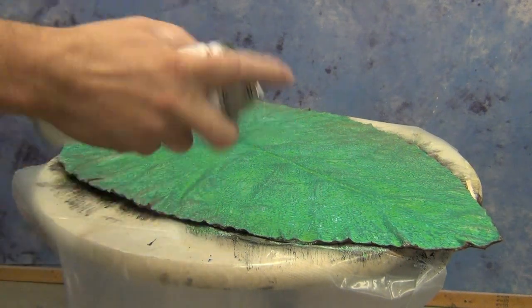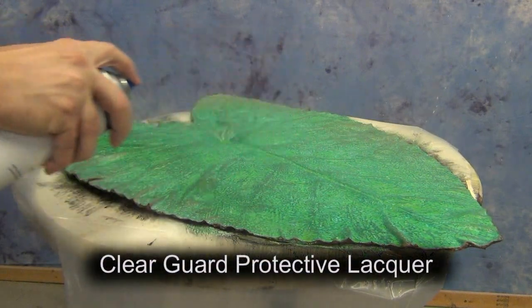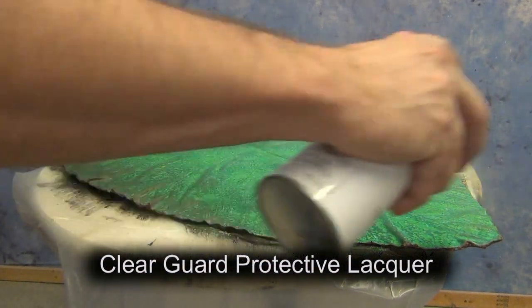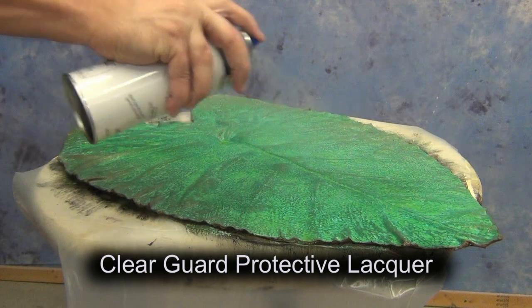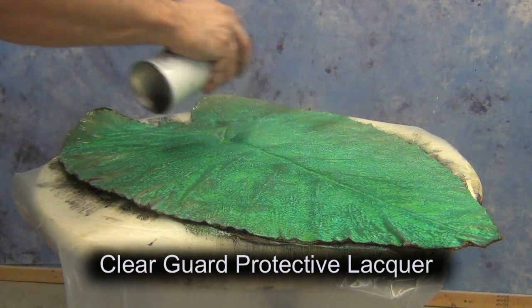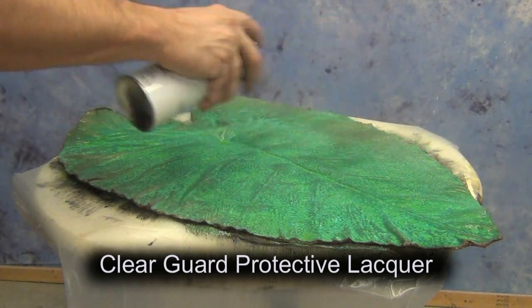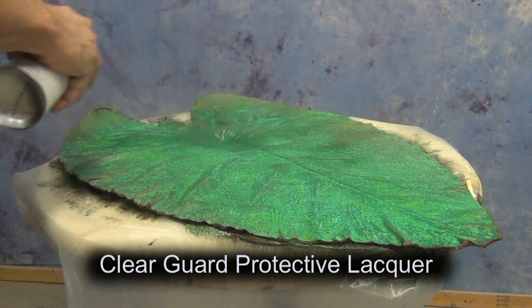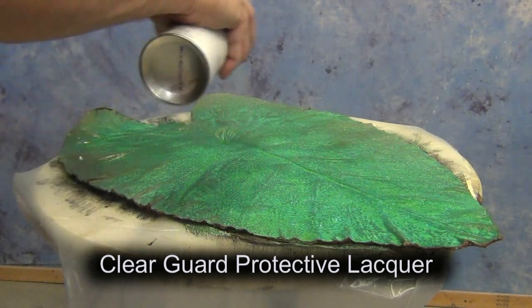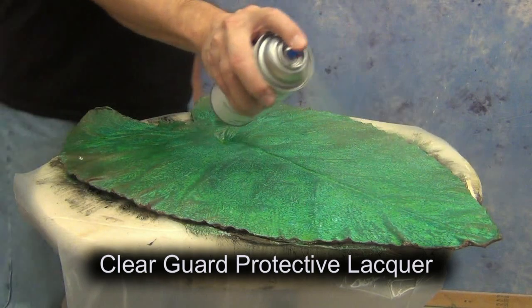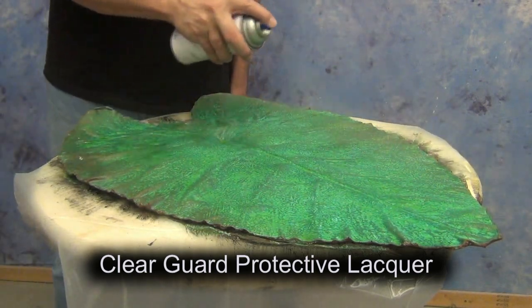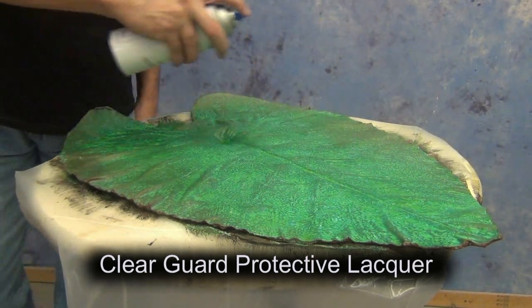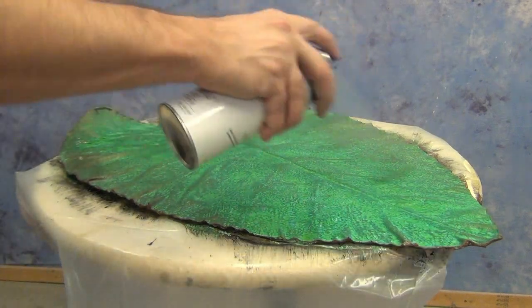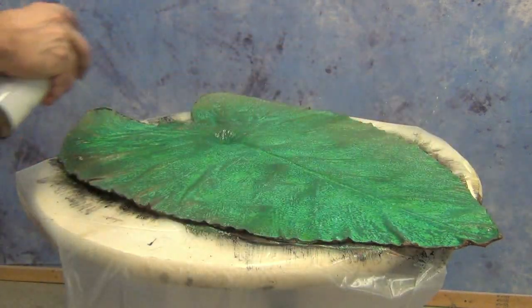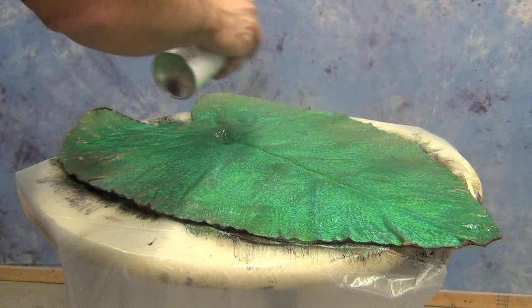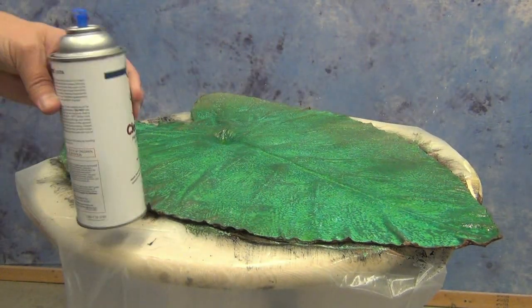And once the color is where we want it and the piece is dry, we're ready to seal it with a clear lacquer. And in this case, we're sealing it with our Clear Guard Lacquer. And this particular lacquer has UV and corrosion inhibitors. And that's real important when you're applying a lacquer over a surface like this that has a patina color to it. Because if it doesn't have that corrosion inhibition, what'll happen is that patina will continue to change as the part ages. Now, if we want, that could be the end right there.